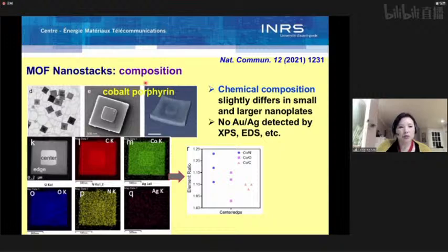We then characterized the chemical composition by doing EDX mapping. We did EDX mapping for this nanostack and for the top and the bottom or edge plates. We can see they all contain carbon, cobalt, oxygen, and nitrogen. From other chemical characterizations, we don't see any detectable gold and silver in this nanostack structure, although we use gold and silver as inducers. We looked at the EDX spectrum data very carefully and characterized the cobalt concentrations. We notice that in the center part there is more cobalt compared to the edge part. So it looks like the top plate has a higher cobalt concentration compared to the bottom nanoplate.